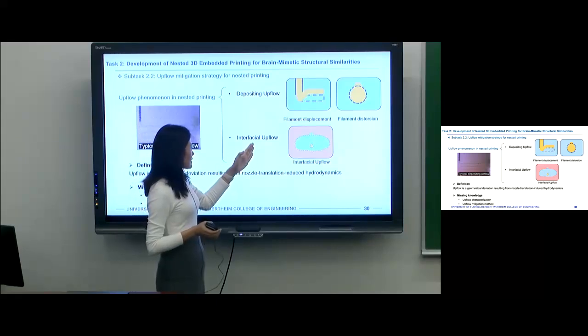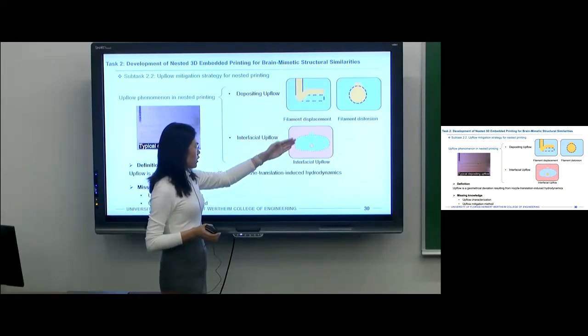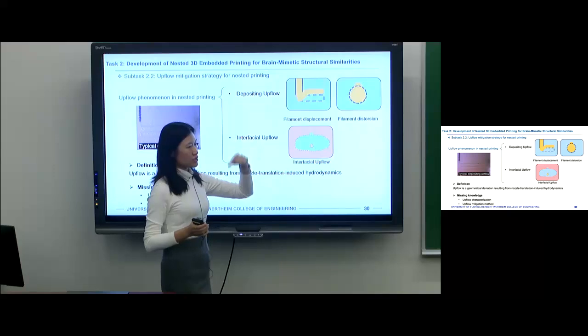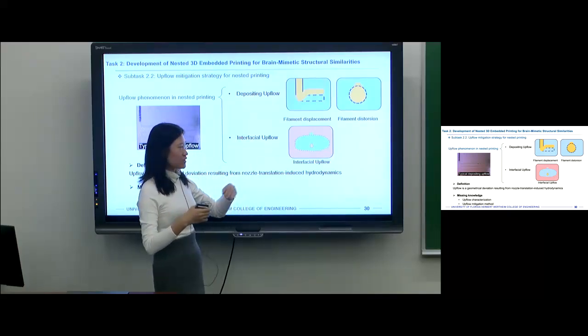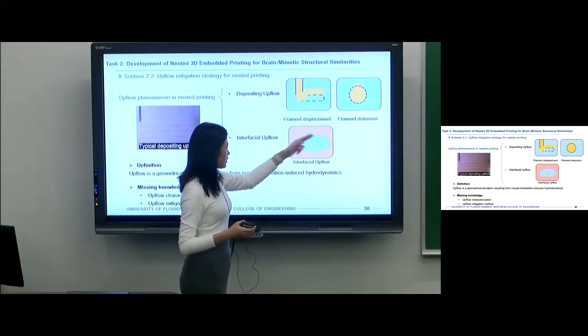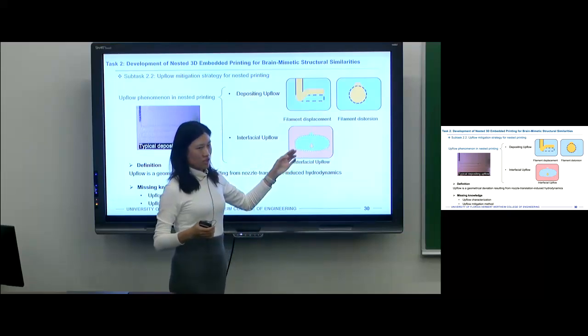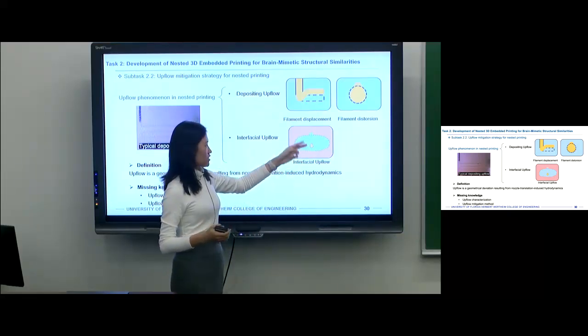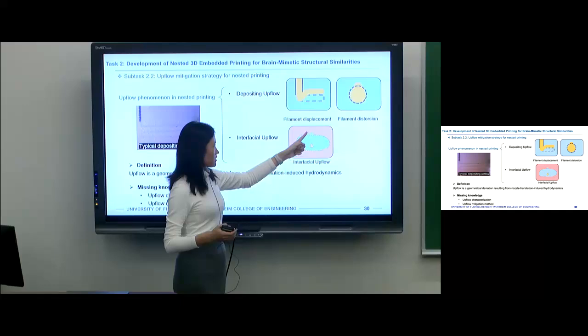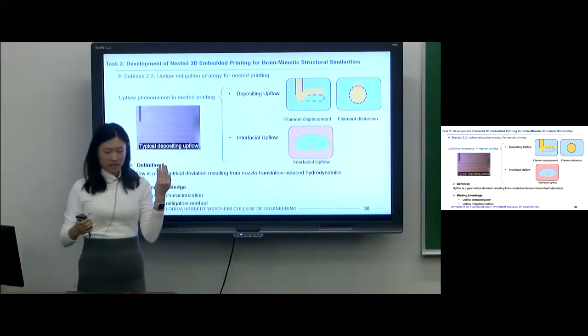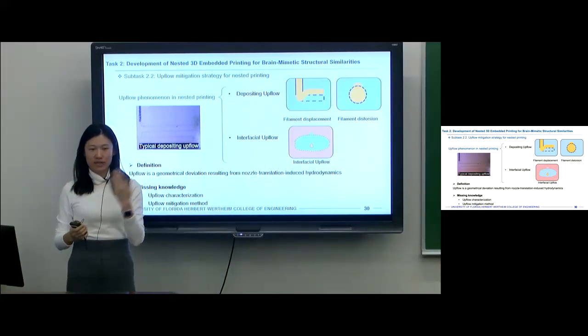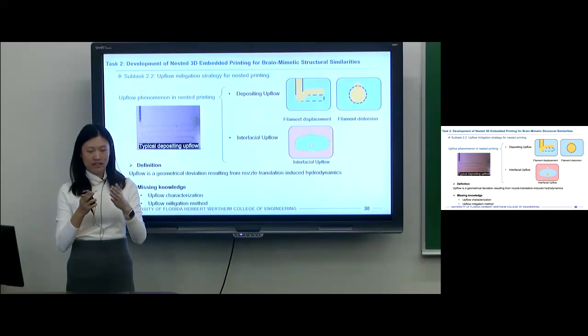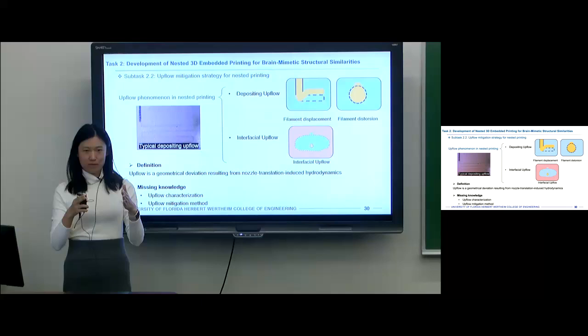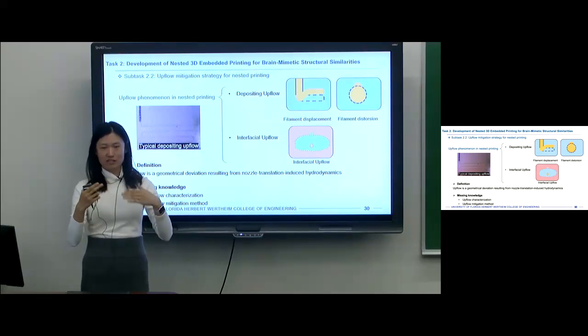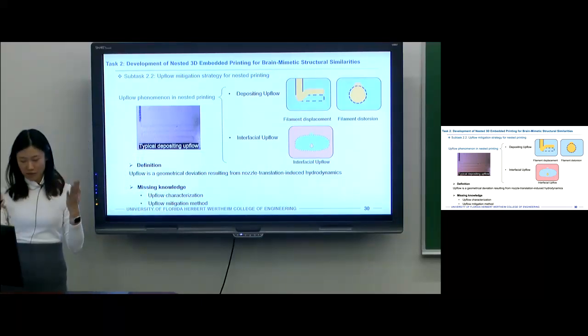Another kind of flow is the interfacial upflow, which means when we deposit the material inside of the pre-existing material, the enclosing structure, also called the previously deposited structure, will be distorted, because this region will have shear force applied on it, so it will become liquid-like. The hydrodynamics will also help distort the previously deposited structure, because it behaves liquid-like and can flow around.